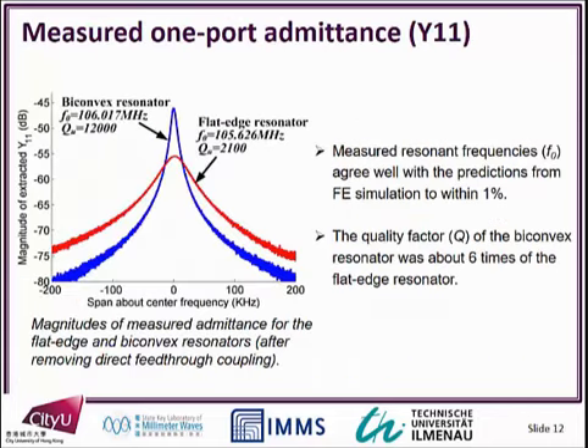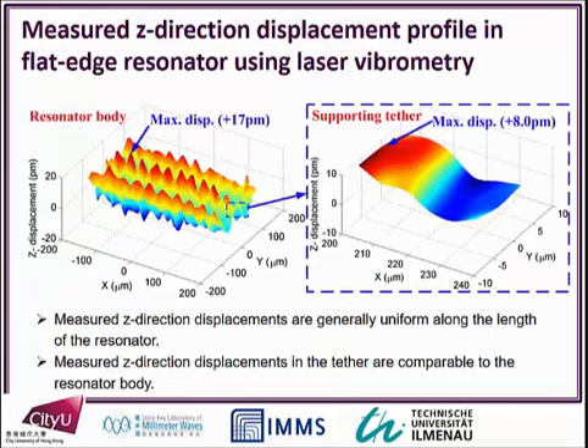Here is a little illustration of what we mean by difference. The resonator with a biconvex, curved edge has a Q of about 12,000 or so, and these are 10 micron thick silicon resonators. The other one, a conventional flat edge, has an average Q of about 2,000 or so. Quite stark differences, so everything lines up in terms of all the properties. If we do a scan with the vibrometer, you see exactly that kind of ridge over here. You get these peaks, and that corresponds to where the nodes are. Doing a scan along the supports themselves, you also see this kind of wave. What is interesting is that the amount of displacement you see down here and over here is pretty much comparable as well.